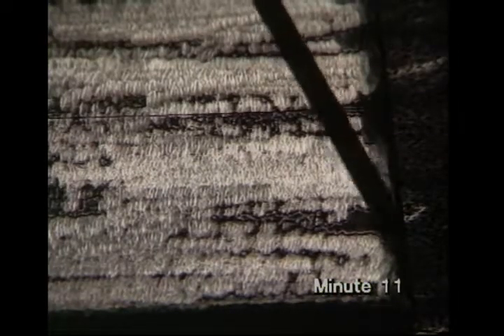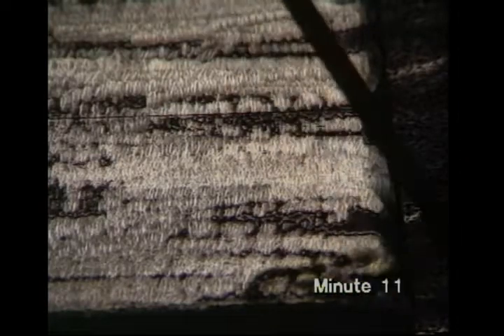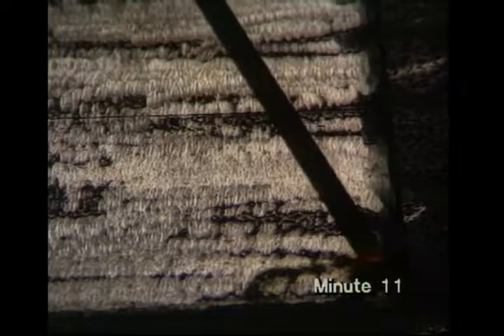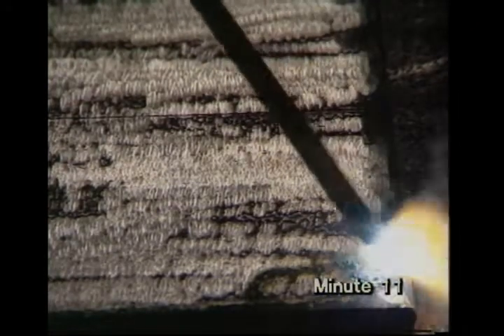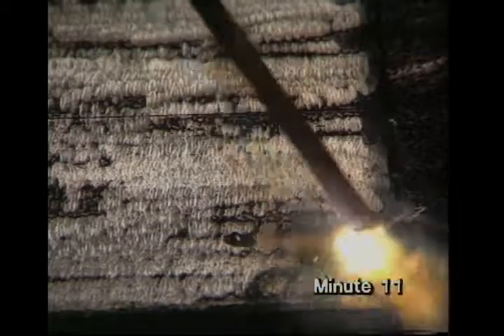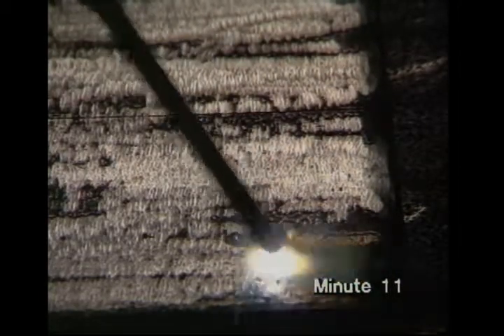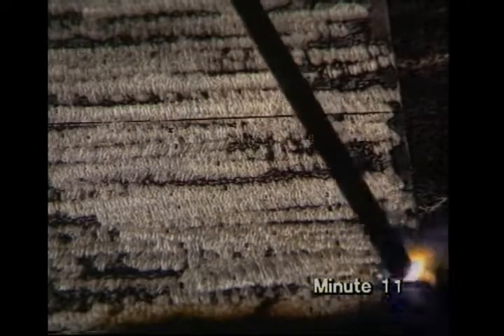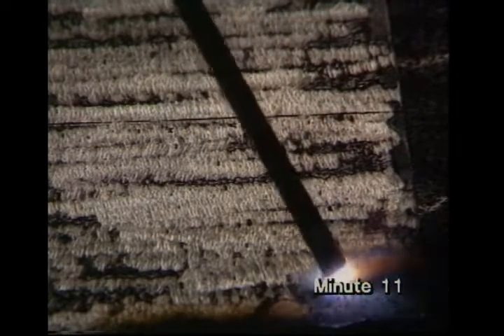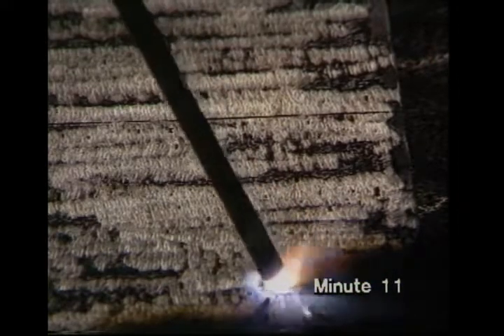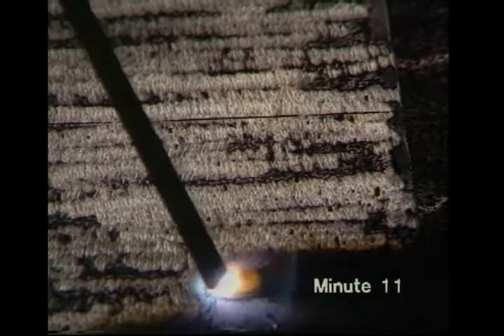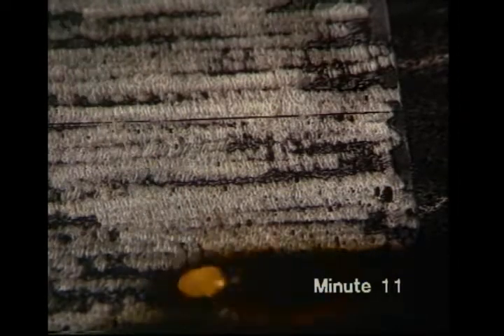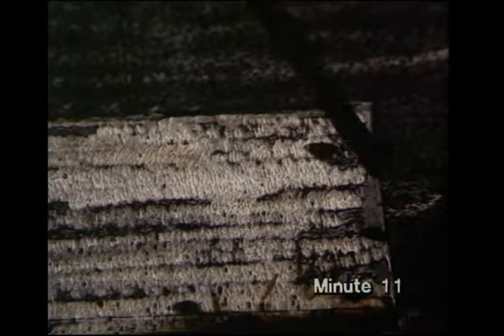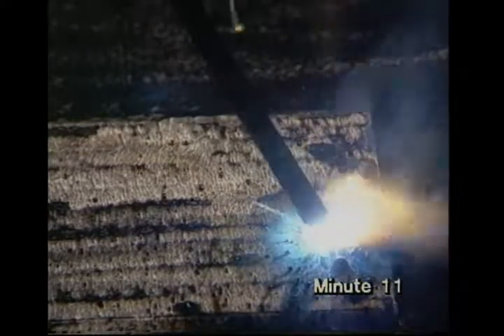If the current is much too low for the size of electrode you're using, it'll be extremely difficult to strike an arc and keep it going steadily. With a bit more current, but not quite enough, even if you can keep the arc going, the weld bead will be small and lumpy. When the current is too high, it'll be easy to strike the arc and keep it going, but the weld bead will be flat and spattery.